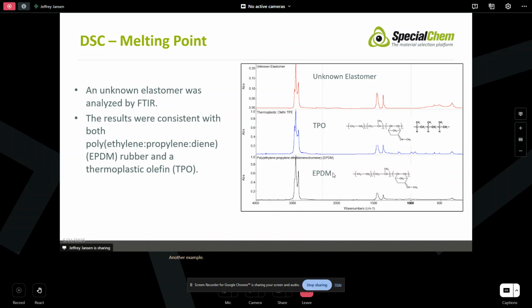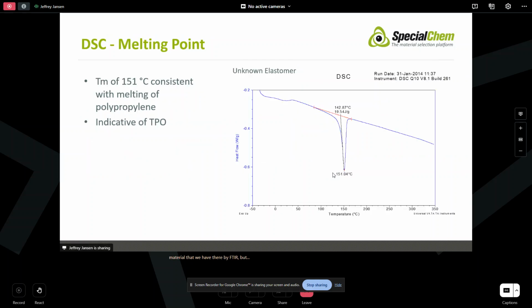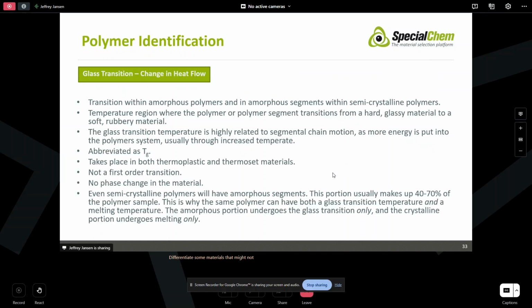Another example is that we may have an unknown elastomeric material. The FTIR spectrum matches pretty well with a thermoplastic olefin, which is a combination of EPDM and polypropylene, as well as EPDM. Really, we can't tell the material that we have there by FTIR, but when we run DSC, we get a melting point about 151. That's what we expect, again, for the polypropylene that's present in that EPDM, as that thermoplastic olefin. Again, what I'm showing you is a variety of different ways, and there are more than this. Hopefully that'll kind of stir your mind as to how you can use DSC to differentiate some materials that might not otherwise be differentiated by test techniques like FTIR.